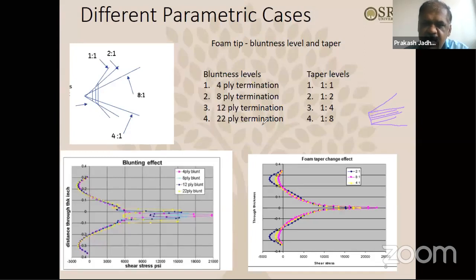Then 22 ply termination. Like this, different cases we tried, and along with the taper level. So we varied this taper level and the bluntness level like this to reach some results, the conclusions. So as you can see, as you vary these different kinds of ply terminations, we get different results.